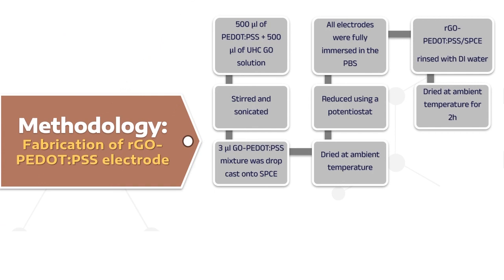On the fabrication of the RGO-PEDOT:PSS electrode, 500 µL of PEDOT:PSS was mixed with 500 µL of UHCGO solution in a small vial. The solution was stirred using a magnetic stirrer and sonicated at 30 degrees Celsius for 10 minutes to obtain a homogeneous nanocomposite mixture. A 3 µL GO-PEDOT:PSS mixture was drop cast onto the working electrode of an SPCE and left to dry at ambient temperature.